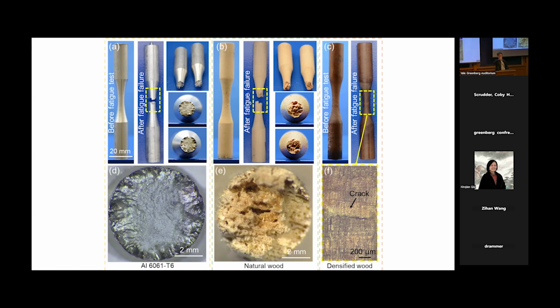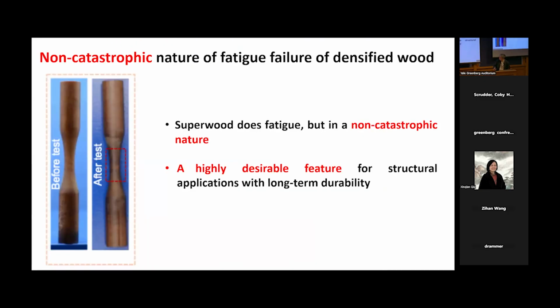So it looks like almost the same thing, but if you look carefully at the thinner section, you start to see cracks over there. But the failure is not catastrophic, okay? So this is the non-catastrophic nature of the fatigue failure of densified wood. And as you can see, this is indeed a highly desirable feature if you want to use this for structural applications, if you cannot eliminate fatigue failure. Okay.